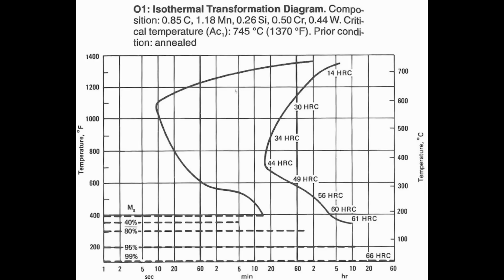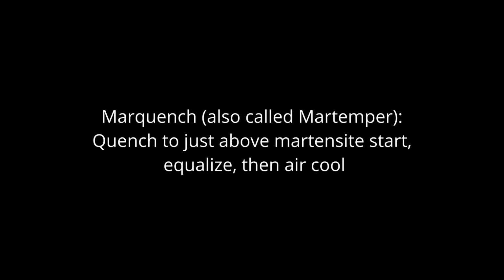So the experiment I did was austempering at 400 degrees and 500 degrees, and then I measured the hardness and the toughness. I also did a mar quench with O1, where I quenched into the 400 degree salt just for a few minutes and pulled it out and air cooled so that it is mostly martensite. Maybe there's a little bit of bainite that formed before I pulled. And we can see if the mar quench led to an improvement in toughness, which is often the reason for mar quenching. You let the steel equalize at that temperature, so everything cools at the same rate.